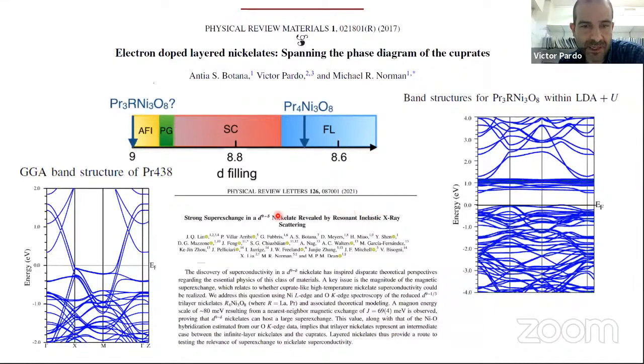What seems clear from recent experiments and calculations is that the magnetic exchange is indeed large, and it wants to be antiferromagnetic. So our calculations seem to be quite correct. At least the comparisons with experiments are reasonable.